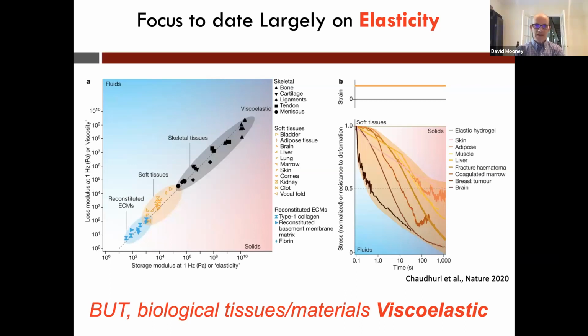However, what we know is that the tissues in our body, the extracellular matrices that surround them, are instead actually viscoelastic, as indicated by the curve here on the left, which shows, for a wide variety of different tissues, soft tissues, skeletal tissues, reconstituted extracellular matrices, the values of the loss modulus and the storage modulus of these materials. And what you can appreciate is pretty much all of these fall on a single line, demonstrating that pretty much all of the materials in our body have intermediate properties of fluids and solids and are viscoelastic and viscoplastic. So the time-dependent mechanical behavior is potentially very relevant in biology as well, in addition to, let's say, the initial modulus.